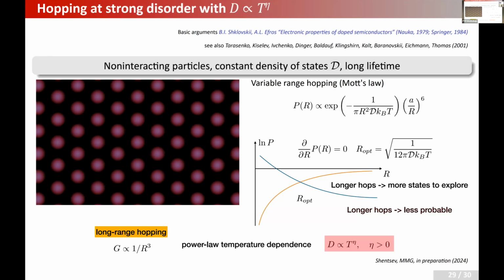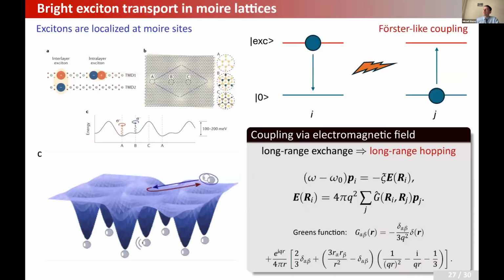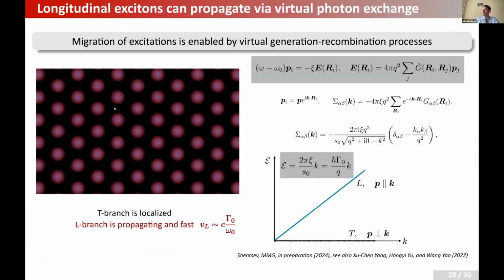So another very basic question is, do the excitons here carry a permanent dipole or not? It depends. Let me say the following. It depends on whether you consider intralayer or interlayer excitons. Which one are you considering? The theory applies to both of those. For intralayer excitons, the coupling to the electromagnetic field is stronger just because of the strong overlap of electron and hole wave functions, but they do not have a static dipole. Interlayer excitons do have static dipoles, so they have stronger interactions, but on the other hand, the oscillator strength is smaller, and the coupling with the electromagnetic field would be smaller, so this branch in the dispersion would be less steep.